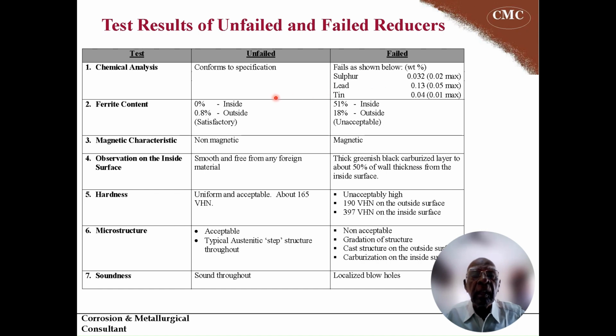You can see the chemical analysis also. There is a variation in the impurities here. Here is the unfailed reducer, it conforms to specification, whereas in the failed reducers, particularly the crack forming impurities like sulfur, lead and tin are very much higher than the maximum limit specified. And this is the same for all other properties. The ferrite content here is satisfactory, at 0.8% on the unfailed new tubes, whereas here it is very high, on a failed cast tube.